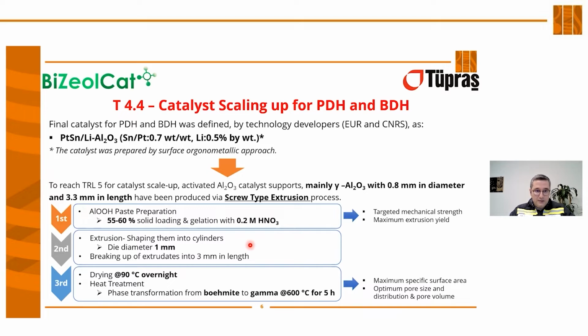Then this paste, with the optimal properties and viscosity, goes through the extrusion process with a die diameter of 1 millimeter, breaking up the extrudate into small lengths. This catalyst was then dried at 90 degrees centigrade overnight.